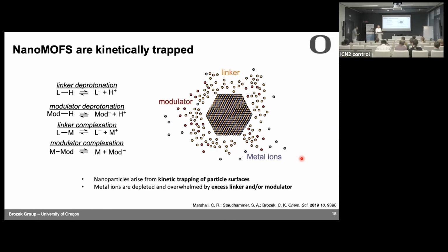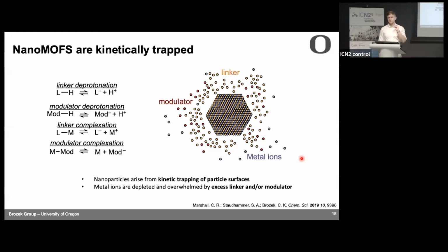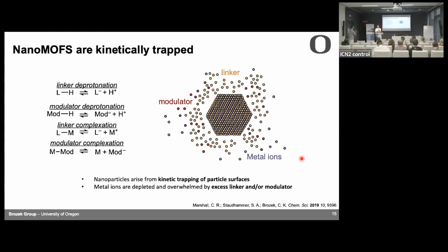Yeah. It's unpublished, but we have work. This is mostly under vacuum, but we've looked at UiO-66 and other MOFs, specifically UiO-66 in the presence of different solvents. The more strongly coordinating the solvent, the less it will redshift. In fact, we're thinking maybe you can use it as a sensor or something, because they're not even wet, they're just exposed to solvent vapor, and you see that it affects the redshifting.